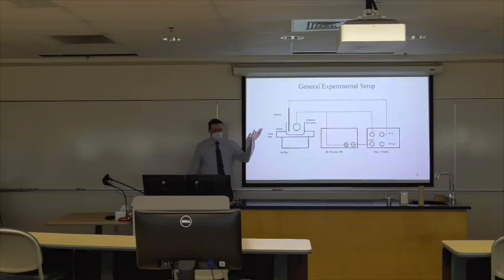The cathode we used in these experiments was a 304 stainless steel piece of metal, and that was it. A really reasonably inexpensive cathode. We didn't use platinum, for example. The aluminum discs were punctured with aluminum wire, reasonably inexpensive, and the back was coated with GB liquid electric tape that you can buy at Lowe's, which is where we bought it. Again, inexpensive, easy to get material.